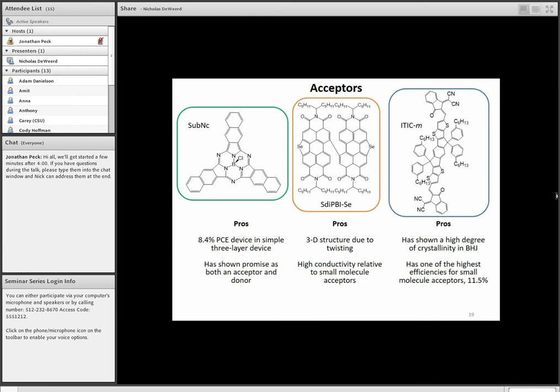So next up to the right, we've got a PDI or perylene diimide derivative. So this was a class of acceptors that's been utilized in the literature for a while now. Basically, they're, in general, very highly conducting and have a really large absorption cross-section. They're very intense absorbers. And they've also been shown to be quite conductive. These are some of the molecules that get the closest in terms of conductivity to a lot of the fullerene acceptors. But this is one of those examples where the researchers have attempted to mimic the 3D structure. So you'll notice that the bond connecting the two molecules in the central orange box is not actually that long. These molecules are actually rotated or twisted with respect to each other, and it's believed that in the morphology they'll adopt something similar to a 3D-like structure that will allow for higher charge delocalization in the bulk heterojunction.